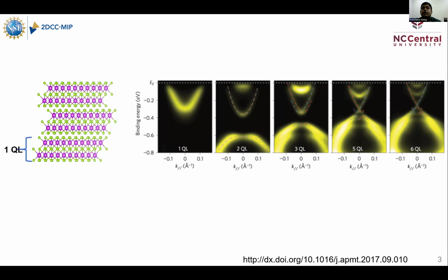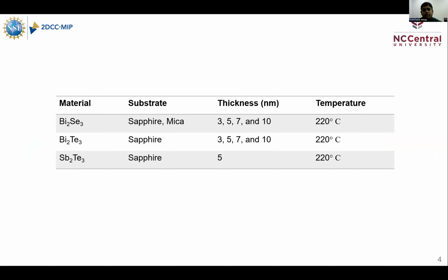With increased thickness, the interlayer interaction forms multiple interlayer hybrid quantum states, which leads to the merging of the band gap and the formation of a topological insulator. This phenomenon we want to use, and we want to see its effect on photo detection properties. To my knowledge, no one has explored it so far in a controlled manner.